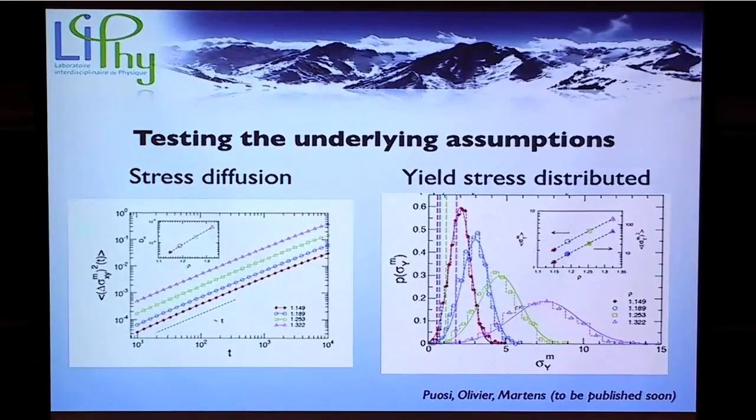And what you measure, okay. We wanted to depict exactly the same thing as the elastoplastic or the mesoscopic model does. That is, we already measure the typical size of the events. Then we divide our system into boxes that have the same size as the size of events. And within the boxes, we measure stress fluctuations.